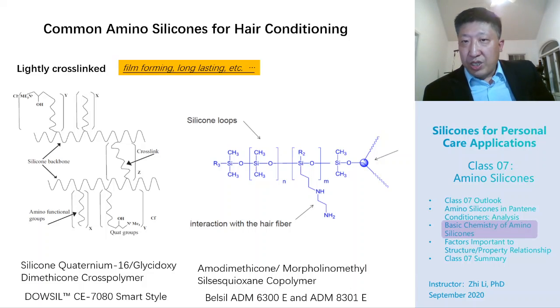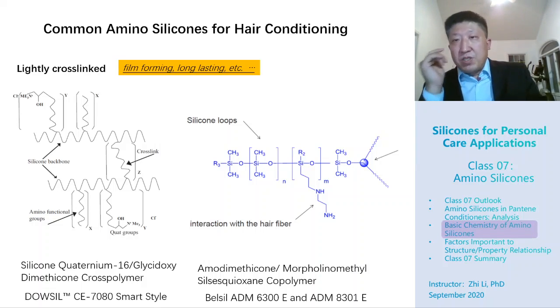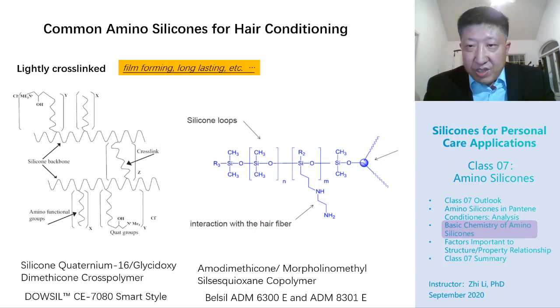the epoxy silicones, and the reaction part is going to form tertiary or quaternium groups and become positively charged. They're able to control the cross-linking density. And this one from Wacker is basically amodimethicone structures, and once it does the reaction, I bet they put some T group silicone building block with 3 functional groups, so they're able to make a kind of T structure out of it, slightly cross-linking by the T structure.